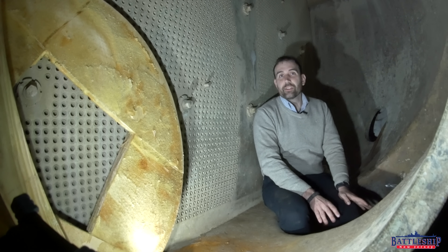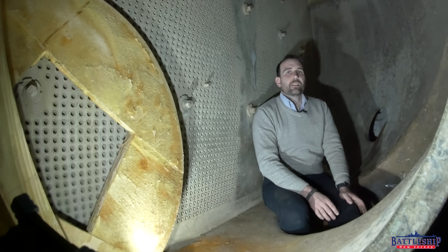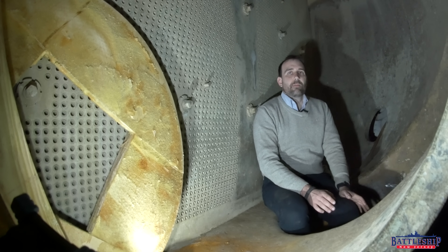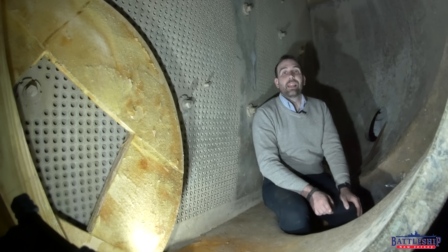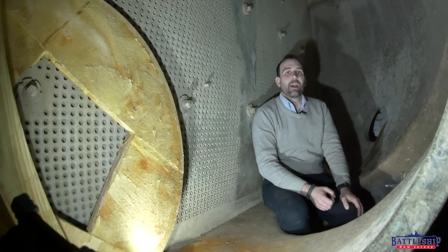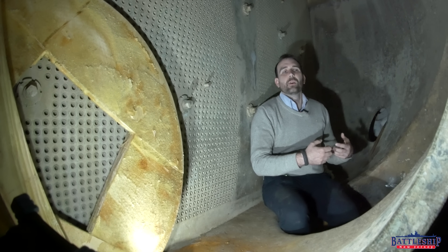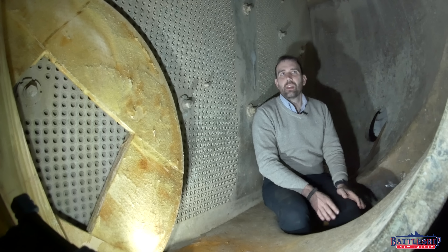Where one of these blanks has failed, it's only a matter of time before others fail. There's a strong chance that when we take the ship out of the water, long after she's started to dry off, we'll still see water leaking out of some of these sea chests — which would mean the blank had failed but the valve on the inside had not. We've built into the project cost the idea that we're going to have to re-weld many of these blanks. Many are fitted with nipples which will allow us to pump compressed air into them to get them up to a certain pressure. If they can hold a couple of pounds of pressure, that means the weld is intact and we're not worried about blowing through rust or a weld bead that might not have been as intact as it should have been. So we're going to air test as many of these blanks as we can.